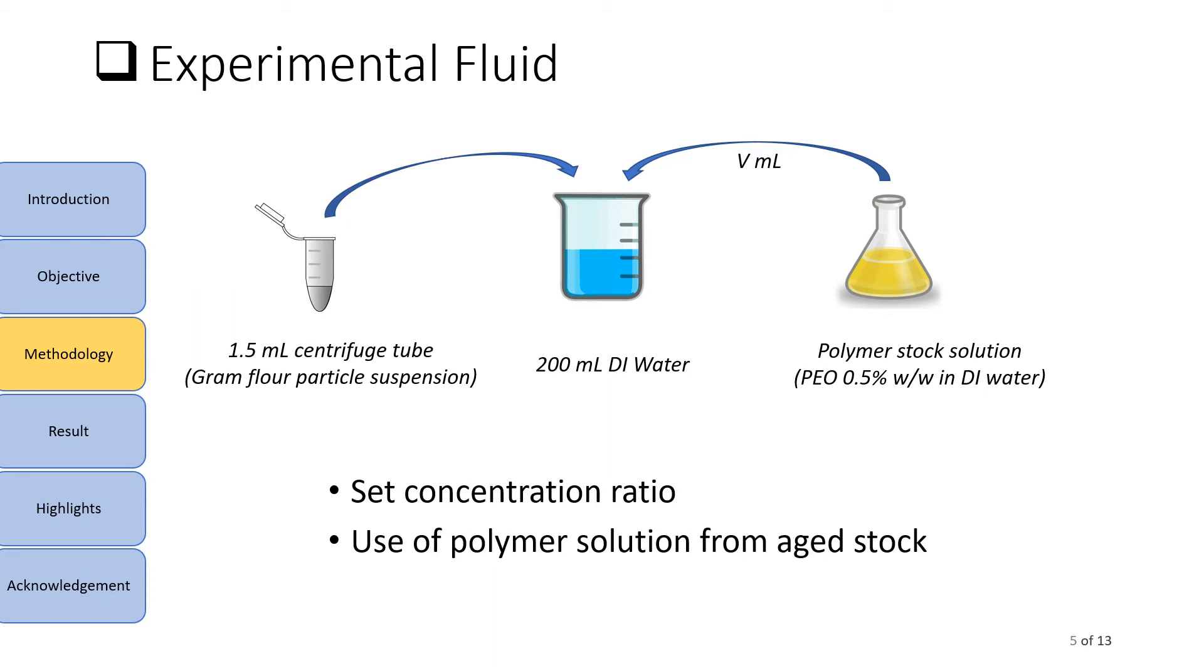Another interesting finding of the present work is that streamer formation occurs only when PEO stock solution is allowed to age for around 15 days. Freshly prepared PEO solution does not show streamer formation.